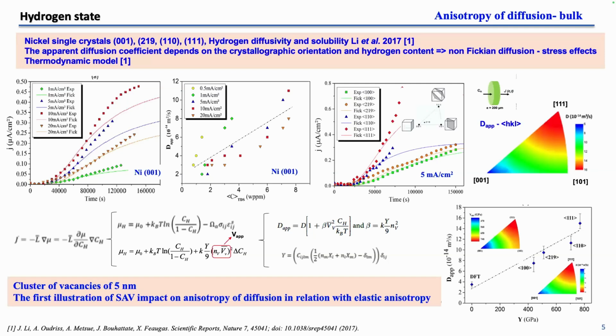Okay, the first result that we need to present was obtained by Jacques Chêne a long time ago, which shows that the diffusivity of hydrogen in nickel single crystal is anisotropic when you add hydrogen. Here we have the evolution of the flux with time for specific orientations, and it shows that this flux depends on the condition of charging. And we can represent the apparent diffusion coefficient as a function of the concentration of hydrogen obtained on this sample by this technique. And we show that the apparent diffusion coefficient increases with the concentration of hydrogen we added to the material.